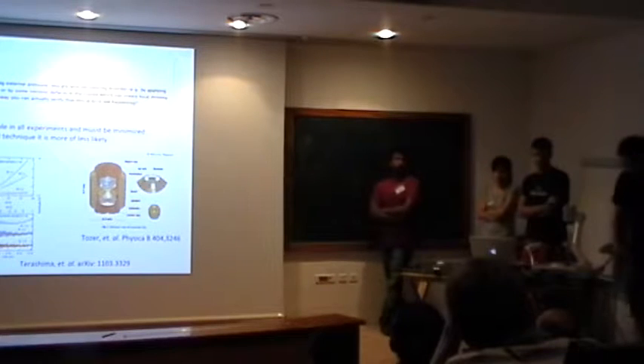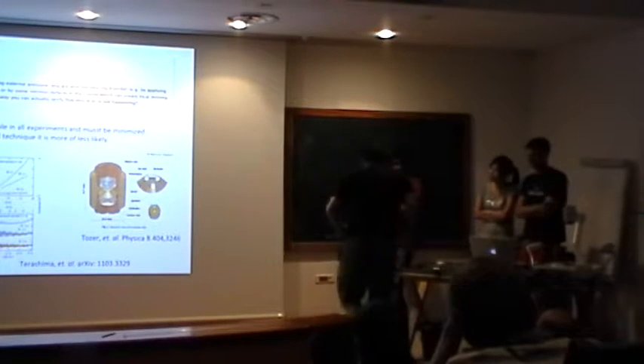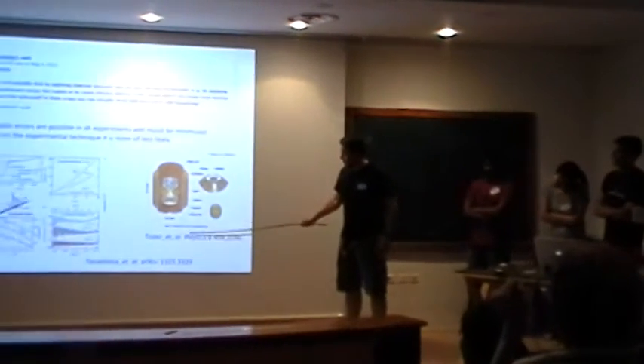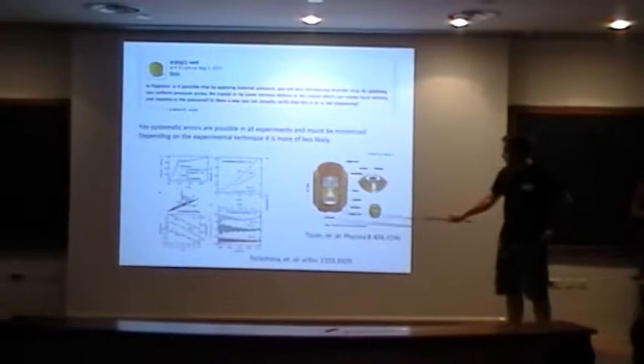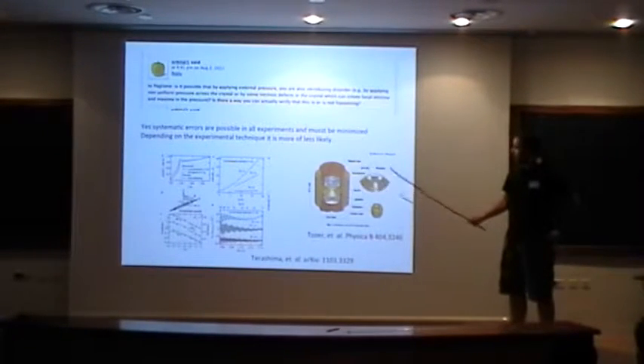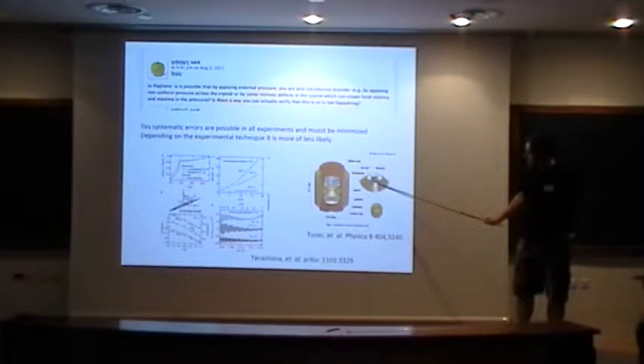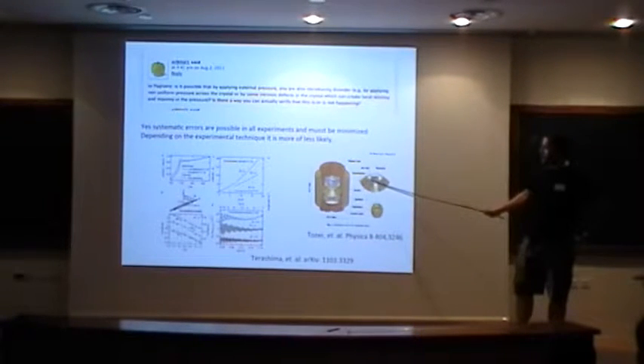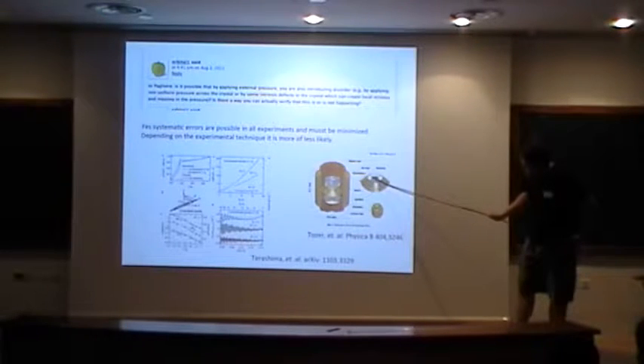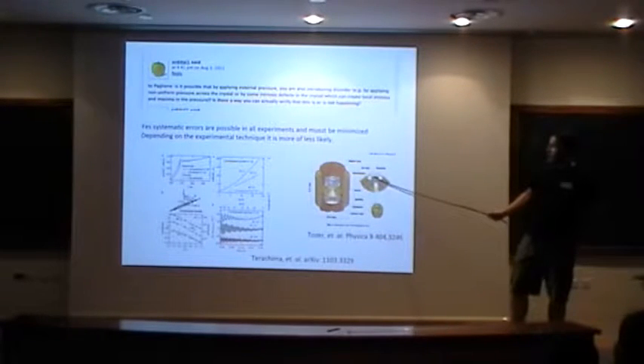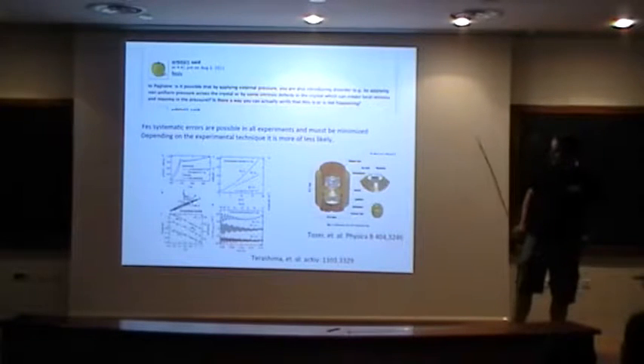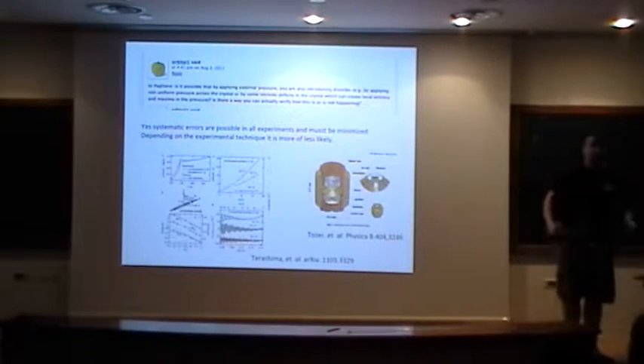Okay, so what I'm showing here is an example of one of those pressure cells, taken from a paper from the Tozer group from Tallahassee. What you see here is basically a diamond cell. They determine the pressure by the line shift in a ruby crystal placed before or close to the cell. And this spot is the sample, and they surround it by a silicone liquid, which basically means they have a hydrostatic pressure.